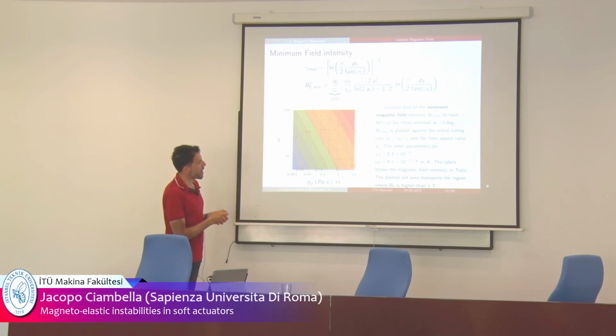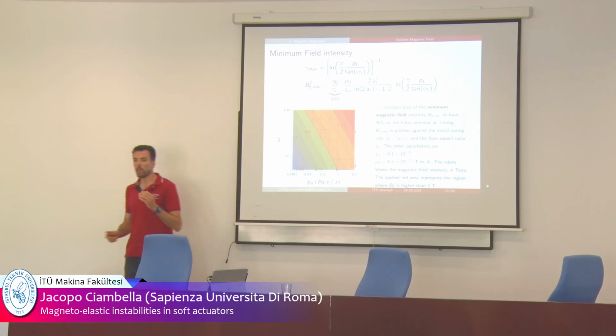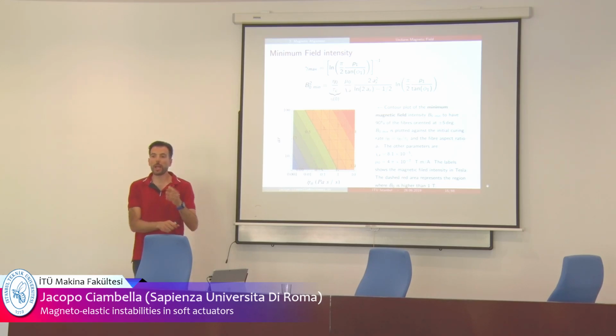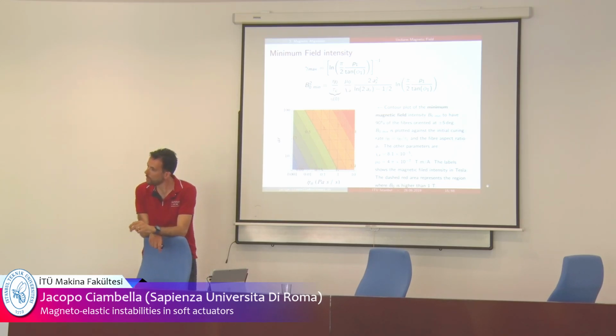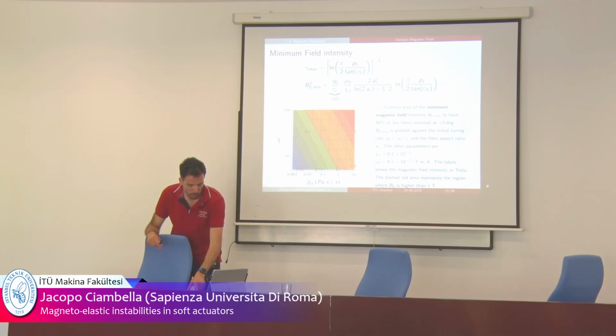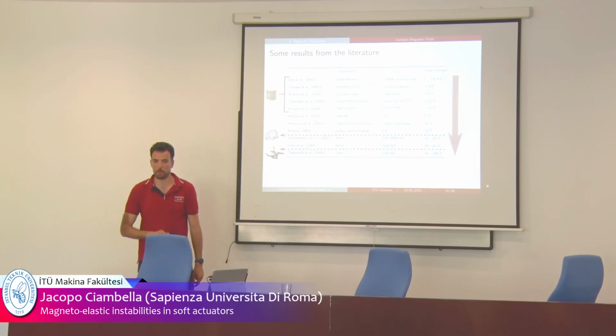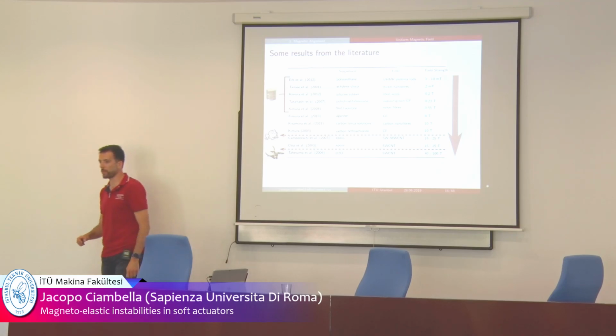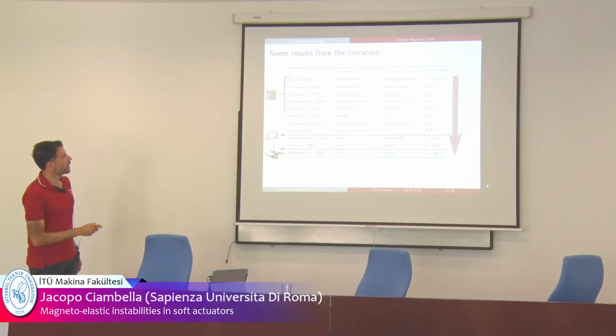Here I plotted in red a region where you need to apply a magnetic field higher than 1 Tesla. Why higher than 1 Tesla? Because more than 1 Tesla is very difficult to obtain experimentally. I want to give you a comparison with this table. These are experimental results. Different types of matrix, different types of filler, and this is the field intensity.